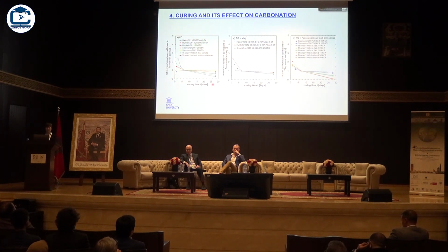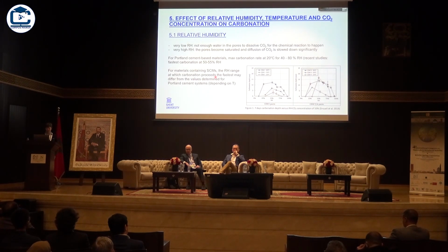So here, just some images showing, for different mixes of Portland cement with slag or with fly ash, the relative carbonation rate versus curing at 7 days. And then you see if you cure shorter, actually for all mix types, it may increase the carbonation rate with a factor of more than 2. On the other hand, if you cure longer, up to 28 days, you may decrease by a factor of more than 2. So it is really a good investment for the future durability of a structure to cure a few days longer at the start, because it's really an investment in future resistance of your structure against carbonation degradation.